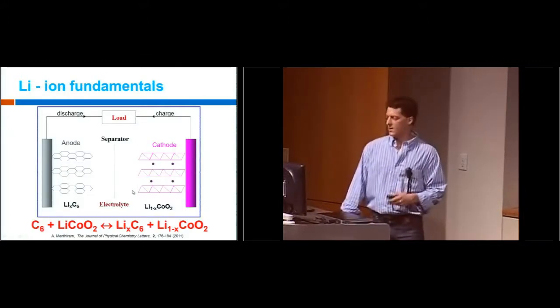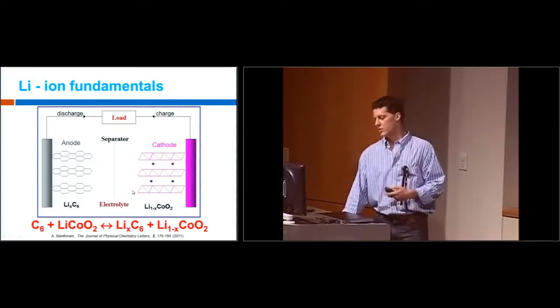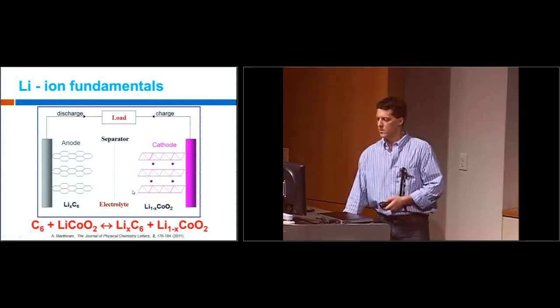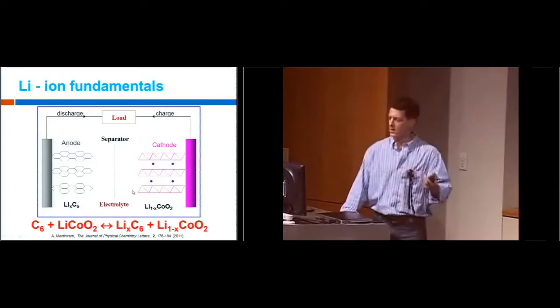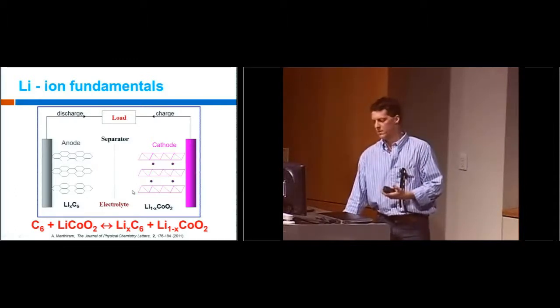Before I talk about lithium-sulfur batteries, I'm going to briefly describe the current lithium-ion batteries that I discussed. These are layered oxide materials for the most part. This is an example of the most common lithium-ion battery right now: the cathode is a structured layered transition metal, and then a graphite anode. During charge and discharge, the lithium ions shuttle between the cathode and the anode. These materials were synthesized to perfectly accommodate the lithium that has to come in and out. They're solid state materials, first of all, and second, very highly conductive materials. Both are important differences compared to lithium-sulfur batteries.